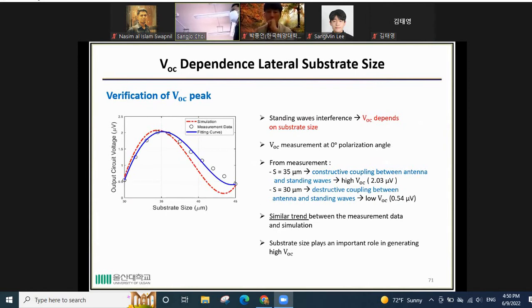Because of the standing wave interference, our VOC depends on the substrate size. From this, we also measure with different substrate sizes at the 0 degree polarization angle. We replicate the device with different substrate sizes and measure. So this is the measurement result of the VOC with different substrate sizes. We can see that the 35 micrometer substrate size provides a high VOC because of the constructive coupling between antenna and standing wave. Then 30 micrometer provides a low VOC because of the destructive coupling between antenna and standing waves. From this measurement, we can see a similar trend between measurement data and the simulation. From this, we can conclude that substrate size plays an important role in generating high VOC of the nano antenna based on the nanothermocouple.